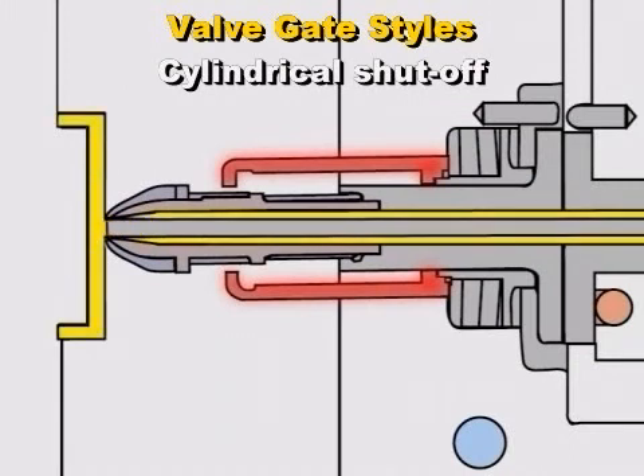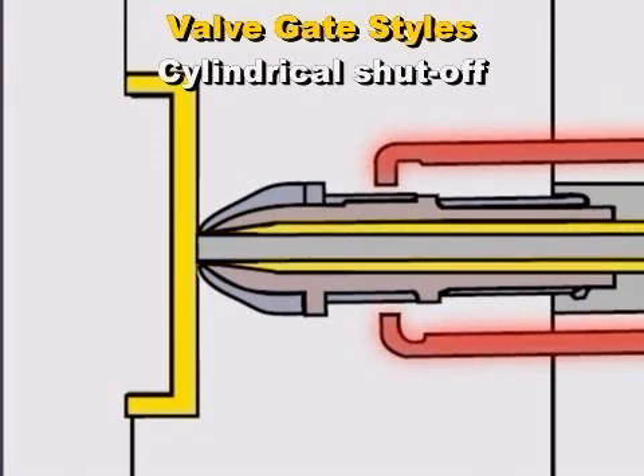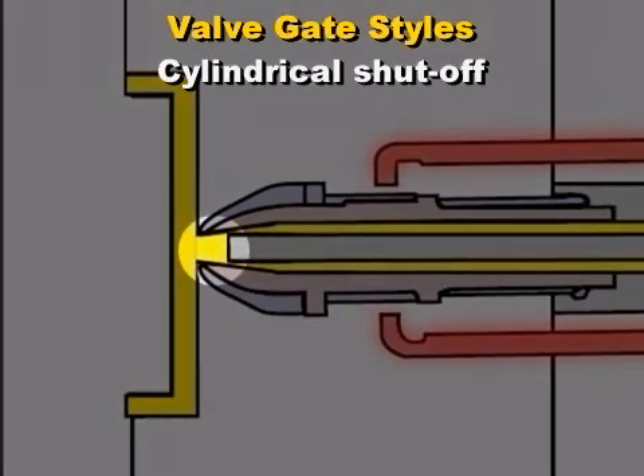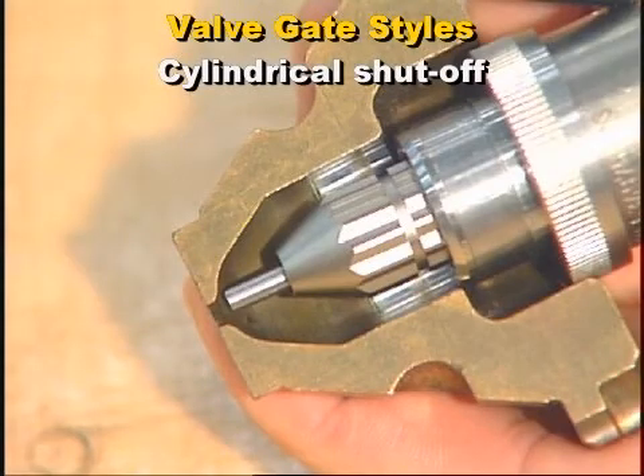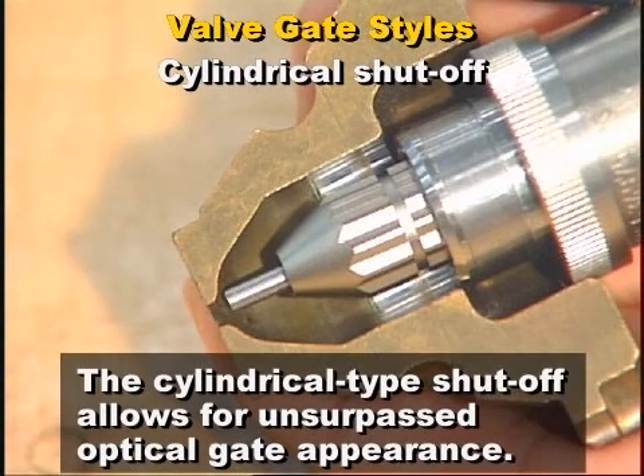With a cylindrical valve stem seal, the valve stem creates gate shutoff without metal-to-metal contact with the use of a tight tolerance slip fit in a cylindrical gate. When the stem moves forward, it acts as a plunger, forcing the melt from the gate opening into the cavity. This gating style relies on the tight tolerance between the valve stem and gate opening for the superior gate quality. This feature also minimizes any gate wear and allows up to 10 million shots without any gate repair. Besides minimized wear, the cylindrical type shutoff allows for unsurpassed optical gate appearance.